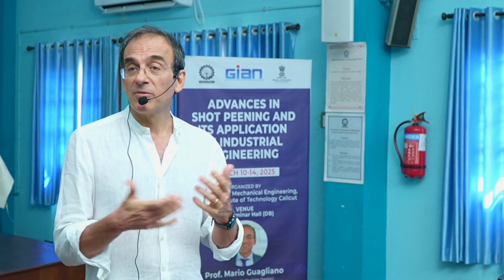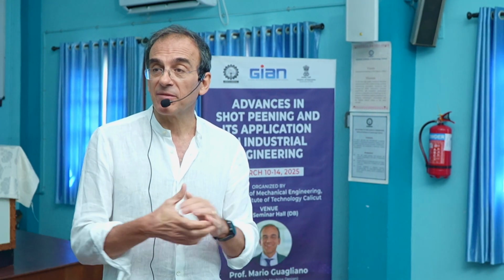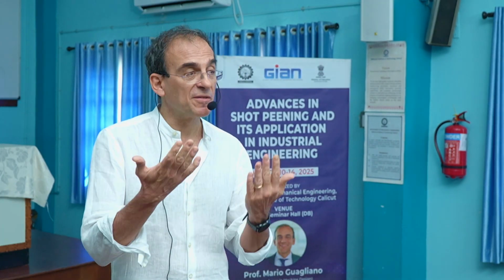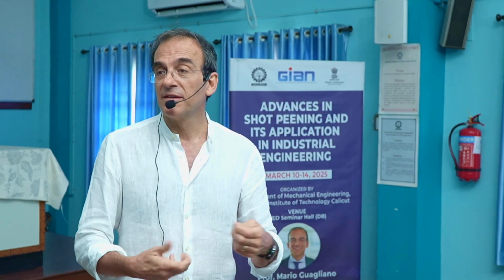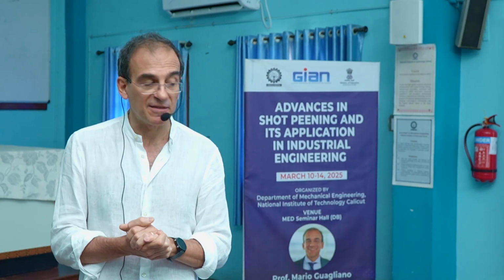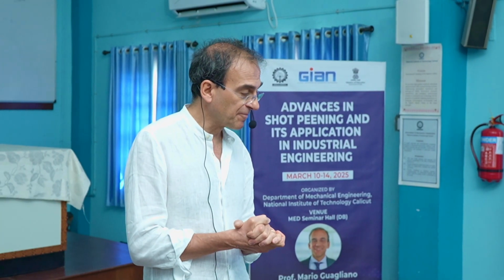And as I said when I talked about severe shot peening, if we consider multidirectional and random impacts, we more easily obtain grain refinement, ultrafine grain refinement down to the nanoscale, let's say, much more easily with this shot peening.